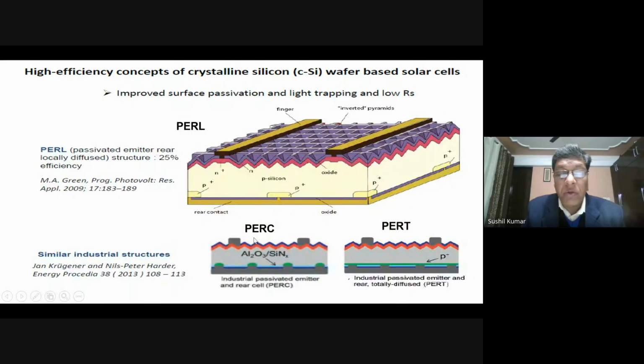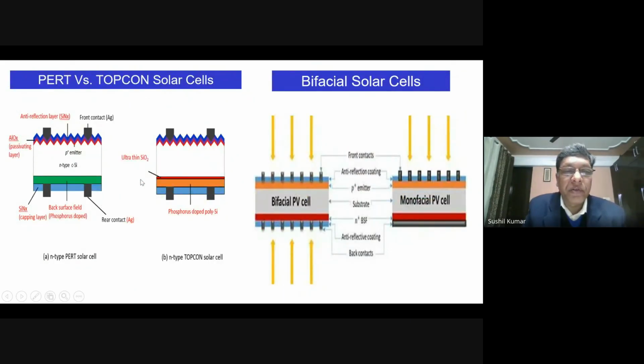But the PERC is very common now. It's about 70% of the market now, of the PERC solar cell. And just 1 or 2 years back, TopCon is coming there with a little difference. Again, I can show you here, the difference is you have a basically thin layer of SiO2. This is what is given in the TopCon solar cell. So now more market share is coming for the TopCon solar cell. So these are the innovations. And this is compared with the PERT solar cell.